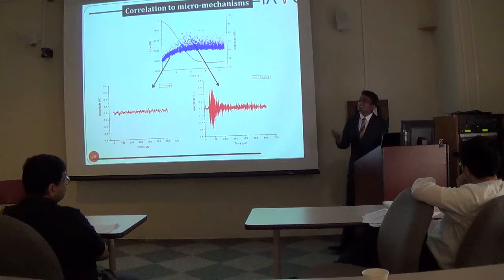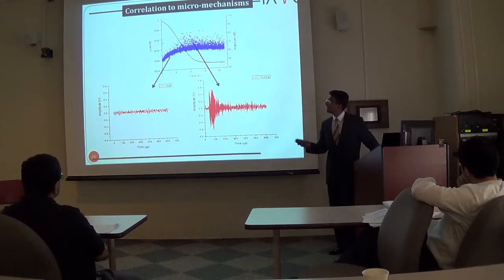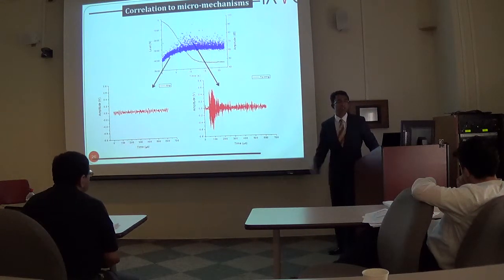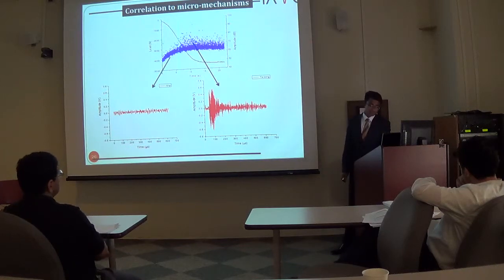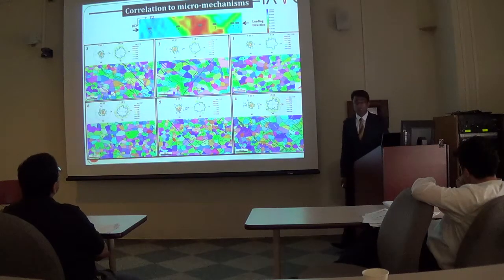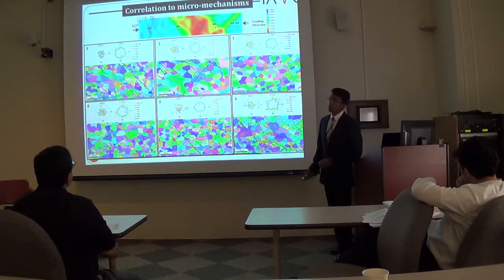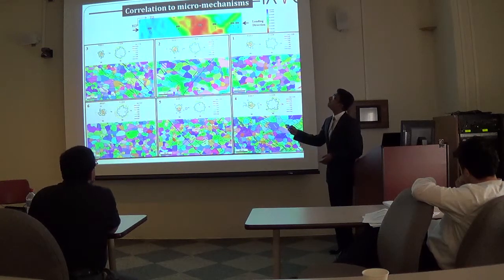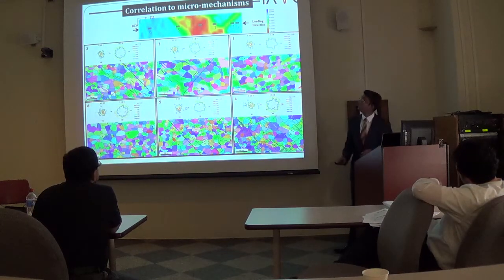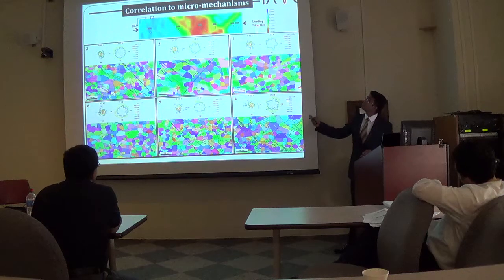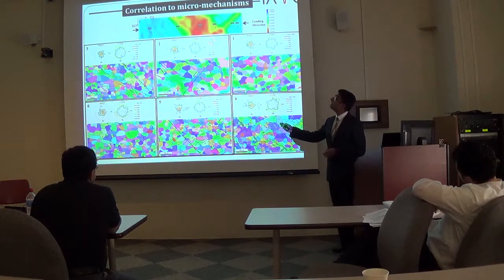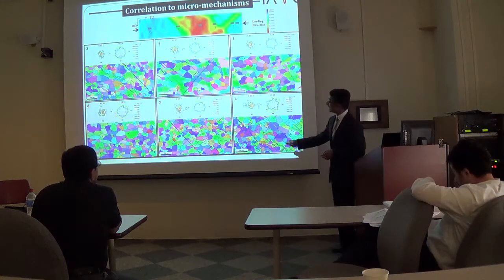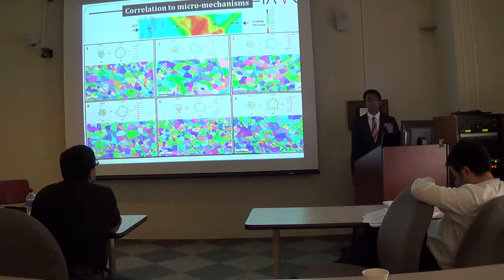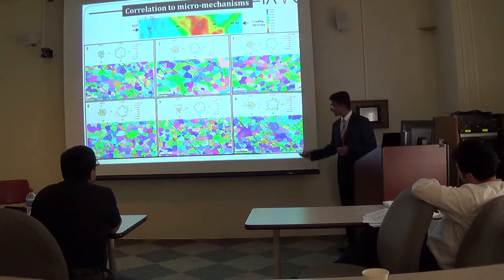Thus, in order to understand the cause or the reason behind the shift from continuous type emissions to burst type emissions, detailed microscopic analysis was performed on the specimens. So exactly where we have these localized strain bands that were picked up by the DIC, microscopic analysis was performed both on the localized strain bands and outside the strain bands. For example, the region inside the strain band, which is 4, you can see is clearly full of a specific micromechanism called twins, as you can see here.